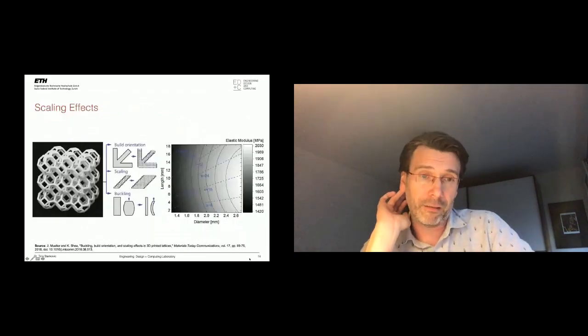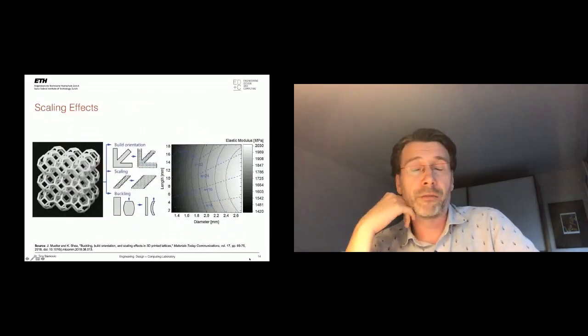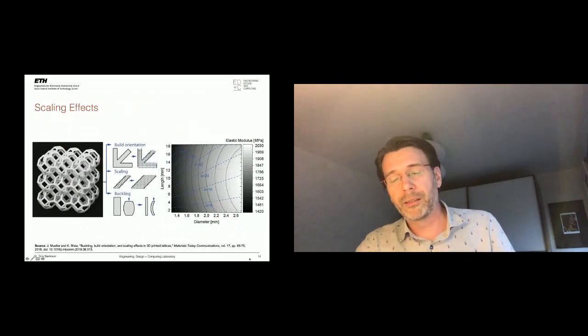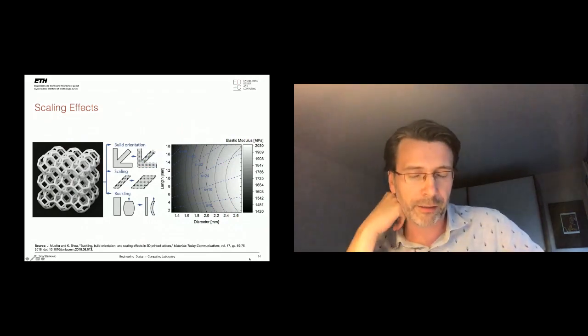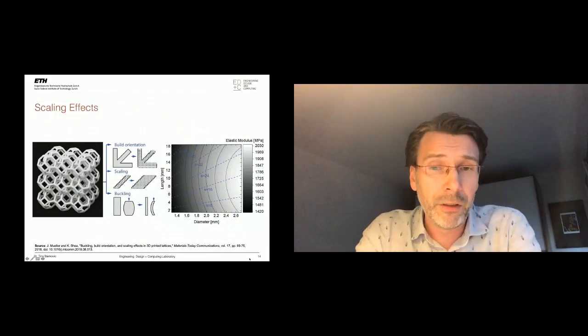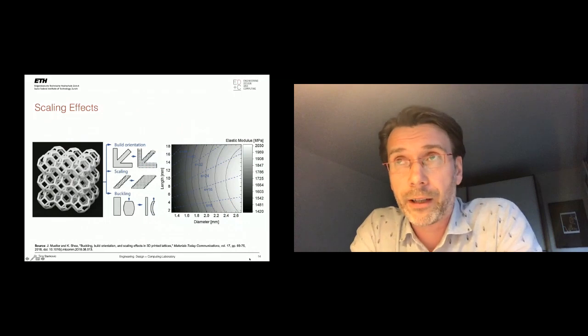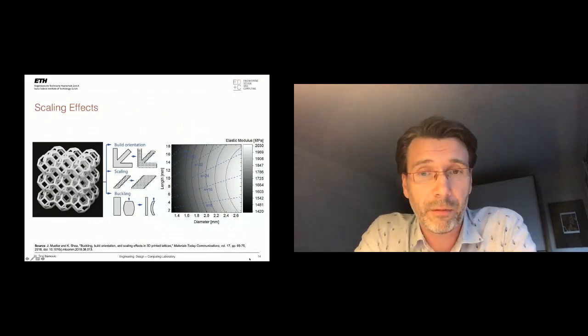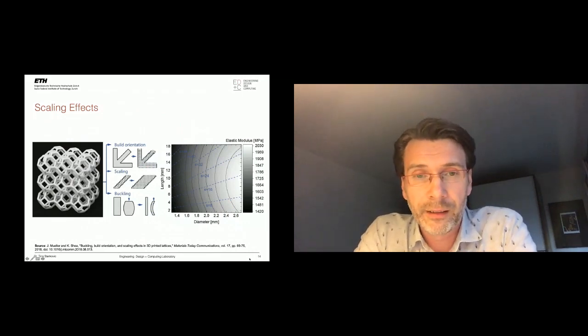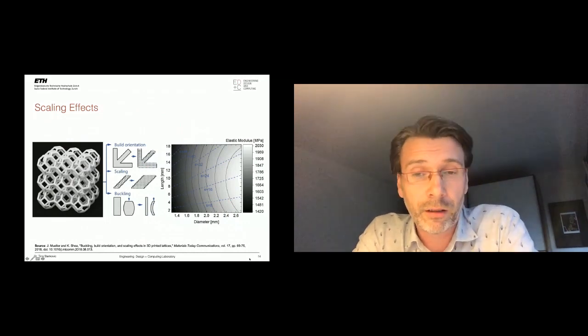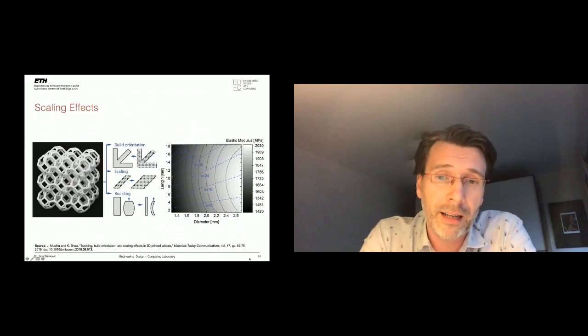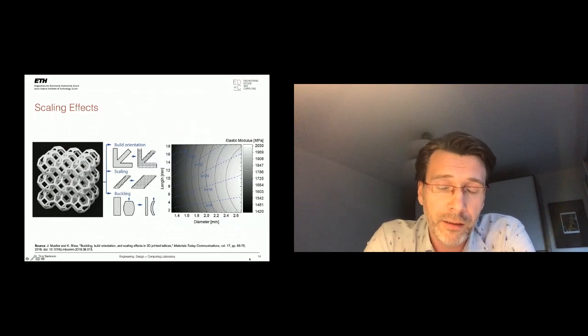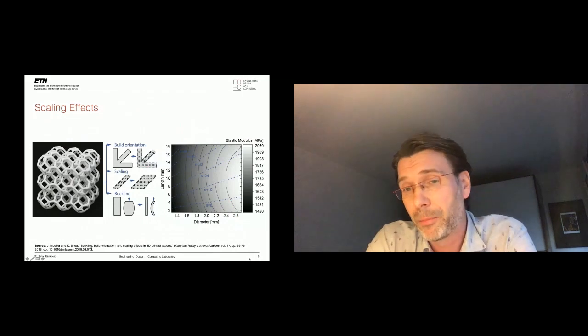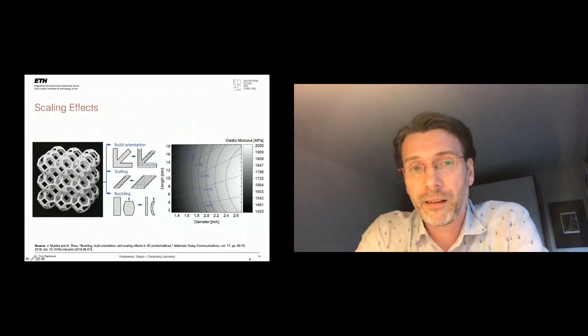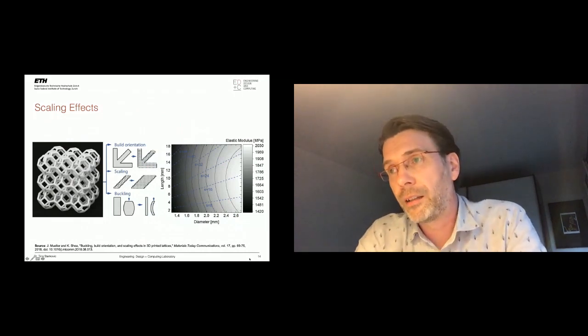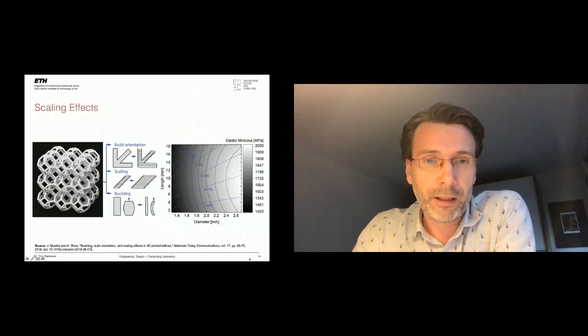We have other scaling effects which are negative, not only positive, because the positive ones really happen on the nano level. For instance, if you print a ceramic part and you have a ceramic crystal that is unbroken, a single crystal, then you can get very nice behavior. But with respect to the macro behavior, we can also have other effects that come in. For instance, if your printer can print to micron level, then this study shows that the effective properties for buckling with respect to the slenderness ratio S are dependent not only on length but on the cross section of the bar. And in the image on the right-hand side, you can see that when the diameter of each member drops beneath 1.4 millimeters, it significantly loses material properties and can buckle easily. So there are many effects that come directly from the imperfections of the printer that directly influence the ideal architected material that we thought we were going to use.